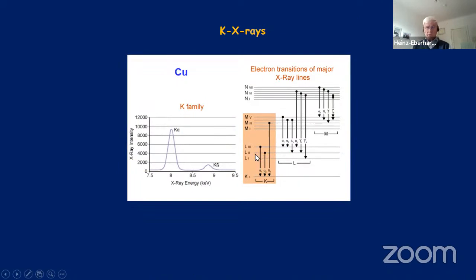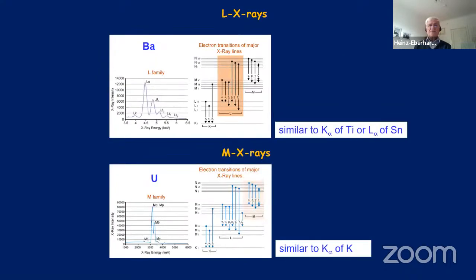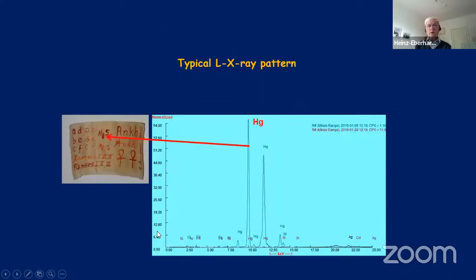In the case of the characteristic X-rays coming out, we have the so-called K family, K alpha and K beta. The typical structure is a high intensity at the lower energy, and a little bit higher, about 10% higher in energy, is the K beta radiation, less in intensity, roughly a factor of 5. In the case of the L family, one gets a more complicated structure, more or less a doublet, about half in the intensities, but with some satellites. In the case of the M family, here for uranium, we come back to a doublet structure with satellites, and the doublet is illustrated here. Now back to the mercury spectrum I showed already. That is the L family. That is the typical structure for the L fluorescence X-ray emission.